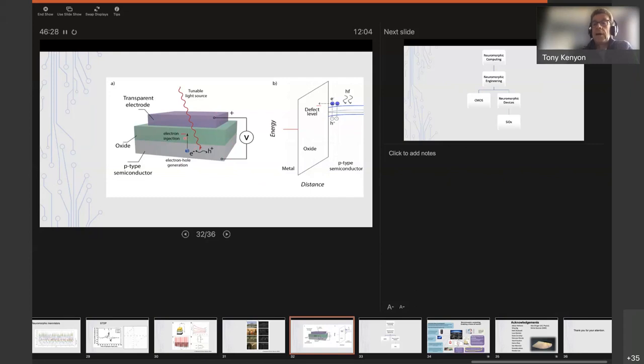And when they're pulled into the oxide, actually injection of electrons, I haven't talked about the model of why we form mobile oxygen, but essentially trapping electrons in the oxide is the first step in that. So by injecting electrons, that creates more mobile oxygen, it creates the filament. So suddenly by switching this light on, we suddenly see the device switch on from being highly resistive to being conductive. So now we've got the possibility of doing some really interesting things with this, what we thought was a very stable oxide to start with. We can change its resistance by very large amounts in a digital way. We can change it in analog ways, so we get almost a continuous variation that allows us to do some interesting, maybe multi-level storage or some processing.